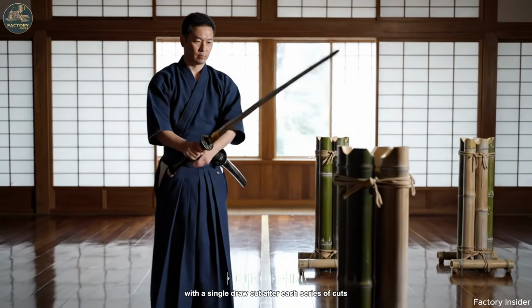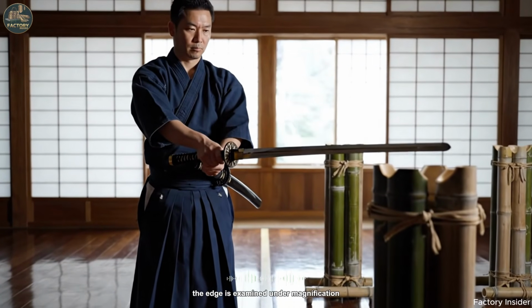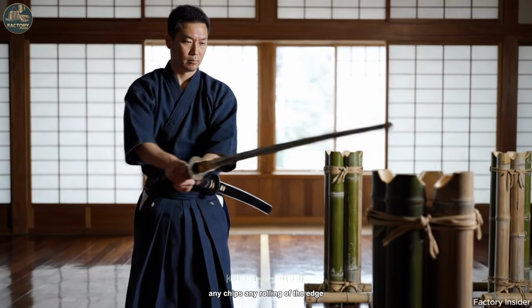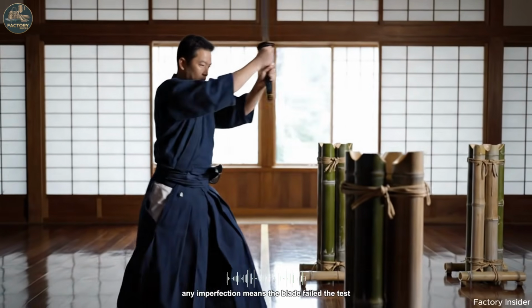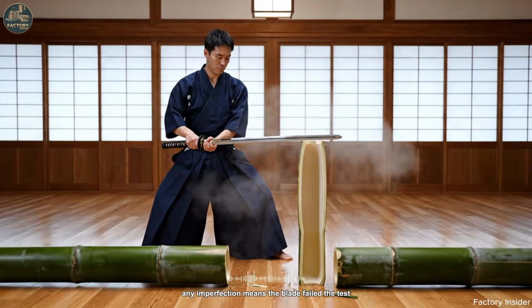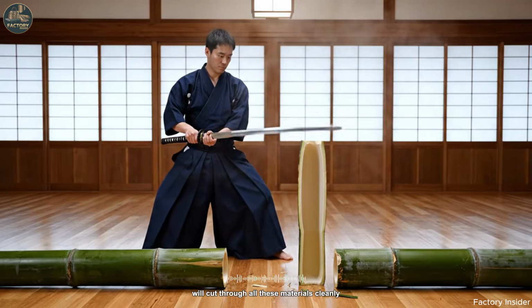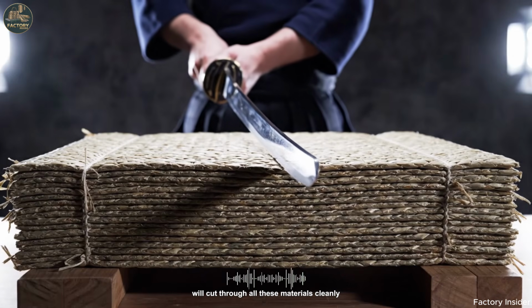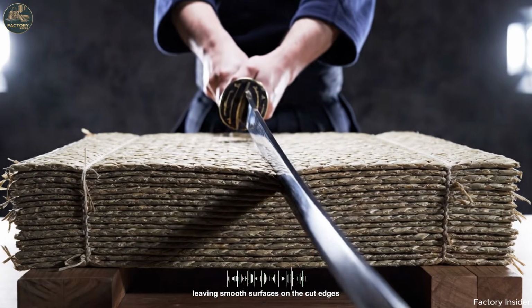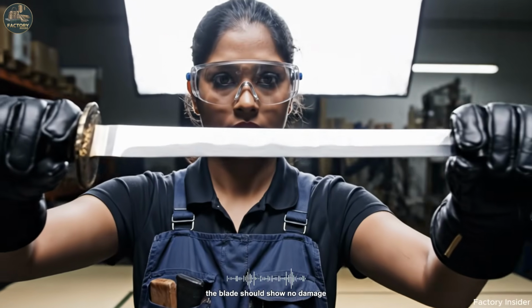After each series of cuts, the edge is examined under magnification. Any chips, any rolling of the edge, any imperfection means the blade failed the test. A properly made katana will cut through all these materials cleanly, leaving smooth surfaces on the cut edges. The blade should show no damage.